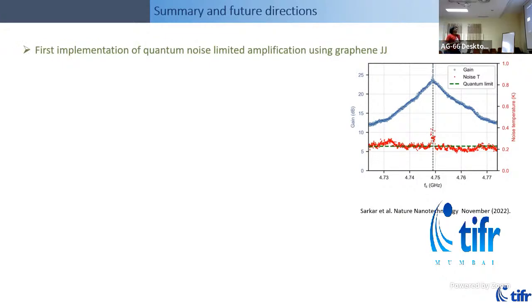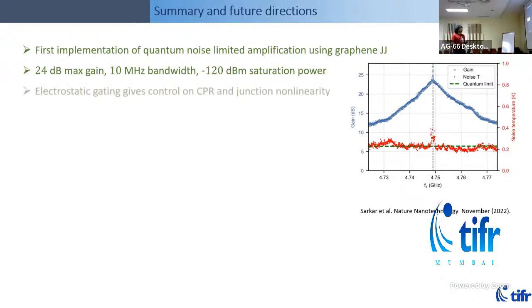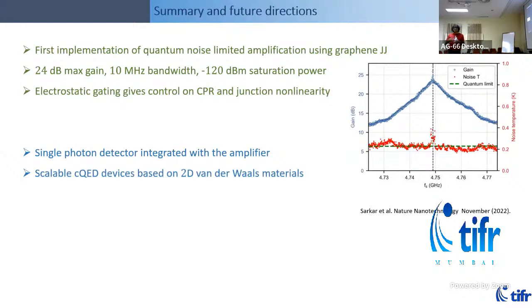So this is the first implementation of this. There are not very many parametric amplifiers. After our work, people have demonstrated this para-amp with other semiconductors, but for a long time, people have been just using aluminum oxide-based technology because those junctions are intrinsically very, very good. But the interest in using para-amps at large magnetic fields is making people look at different possibilities. What we are interested in is trying to use these amplifiers with the sensor embedded inside. So use the graphene as a sensor and use this nonlinearity to make a sensor which is more sensitive than